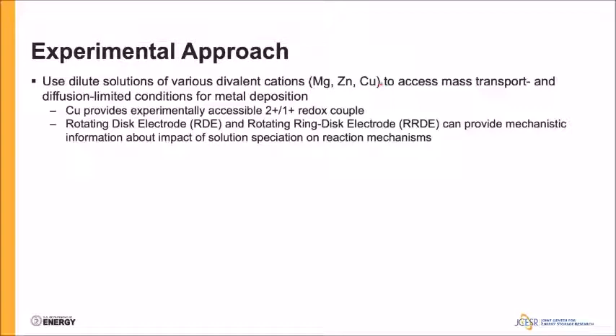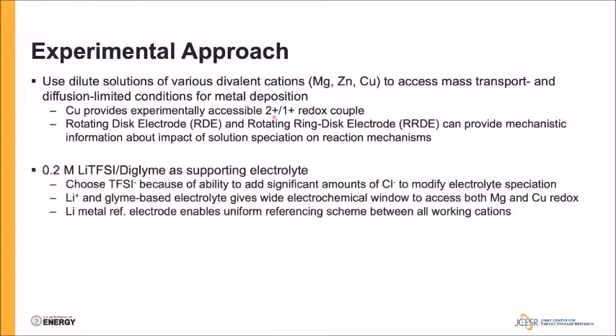The other advantage of going to dilute solution is we can use rotating disk and rotating ring disk electrode methods to look at, again, more mechanistic information about the impact of solution speciation on the response. Because we're working with dilute concentrations of our working cations, we need a supporting electrolyte, and in this case, we're going to use a lithium-based electrolyte with TFSI and diglyme.